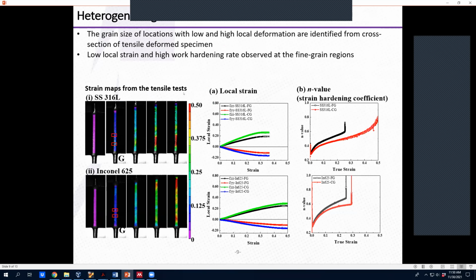For that, we performed digital image correlation analysis, and we saw that for both materials, under uniaxial tensile test, there were periodic regions of high and low local strain. With that, we took local strain gauges in the fine grain region and the columnar grain region. We found that in both materials, the fine grain region shows low local strain and also a higher work hardening rate, which we relate to the Hall-Petch effect, or grain boundary strengthening, because of the grain size in the fine grain region.